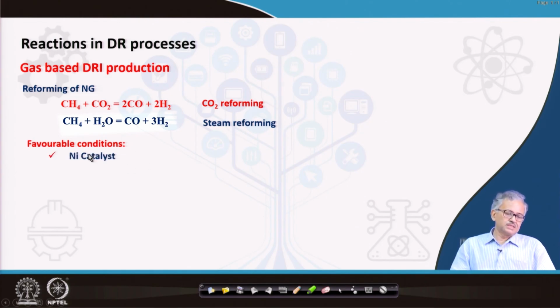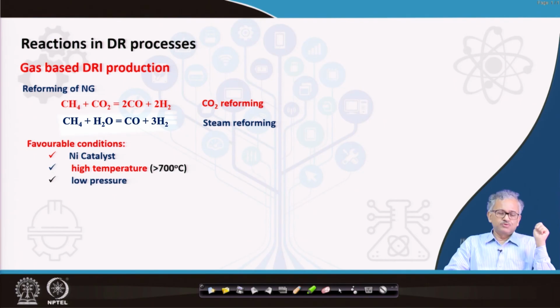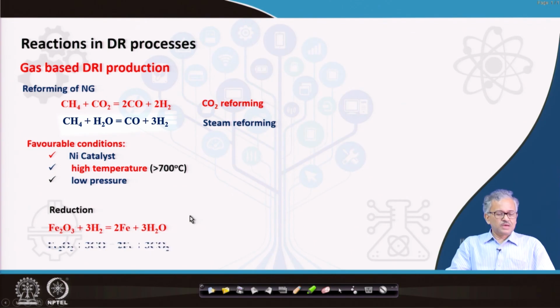Favorable conditions are there. For all these reforming processes you need a catalyst, otherwise the process is not very fast. The presence of a nickel catalyst makes this process very fast, and the temperature should be comparatively higher, greater than 700 degrees centigrade, and you have to use a low pressure. Obviously you can find in this reaction that 4 gaseous moles are produced out of 2 moles of gaseous reactant, so the pressure will increase. So at low pressure this reaction will move in the forward direction. The reduction is basically Fe2O3 with hydrogen forming Fe and H2O, and it can also be reduced by CO. So this is the overall reaction.